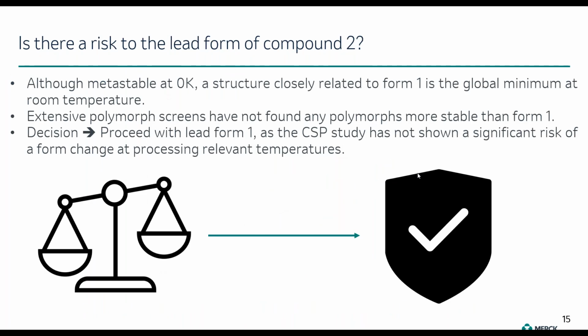So how did we digest this data and come to a consensus? Although it is metastable at 0 Kelvin in lattice energy, a structure closely related to form 1 is the global minimum at room temperature. At the same time, the extensive experimental polymorph screen did not find any polymorph more stable than form 1. So we decided to proceed with lead form 1, as the CSP study, despite these complications, did not show any significant risk of a form change at processing relevant temperatures.